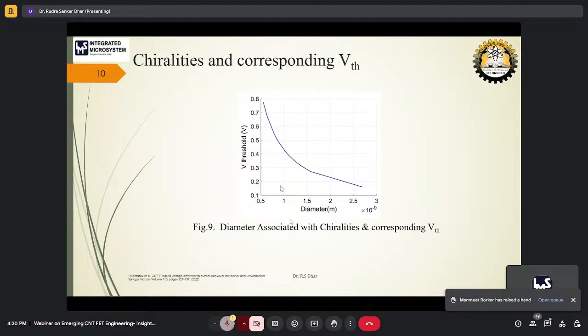Also, as I said, the diameter size changes based on the chiralities. That is what we can see from this graph also. This is the threshold voltage change with increase in diameter of our tube. If the diameter is increasing, the threshold voltage is decreasing to quite an extent, an exponential decrease, as we can see. So we should choose the diameter accordingly. We cannot go for a very small option, because the threshold voltage of the device needs to be optimized for a FET. So we went for 1.9, which is giving a threshold voltage of around 0.3. Okay.